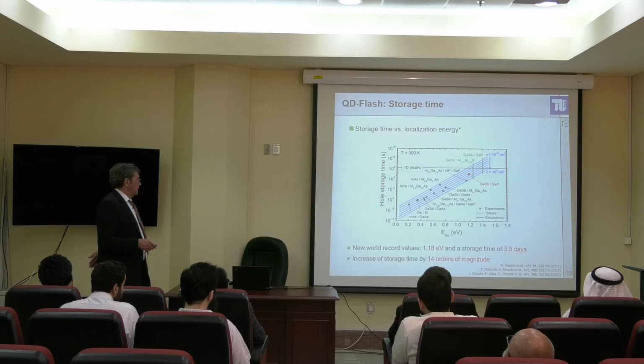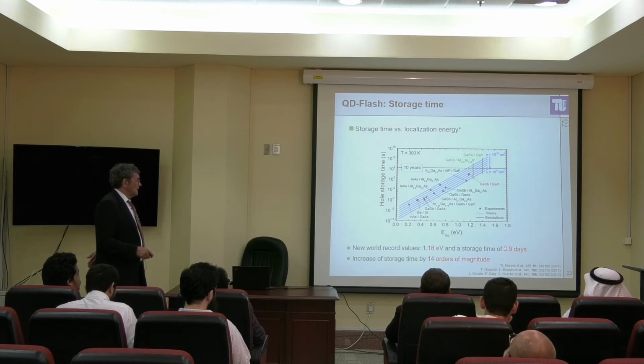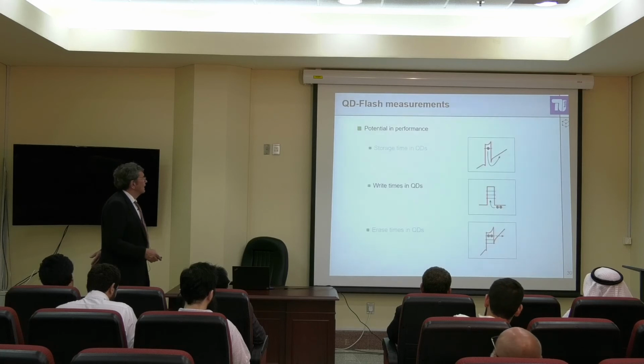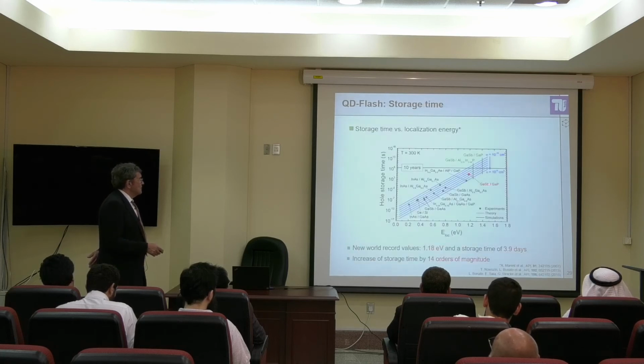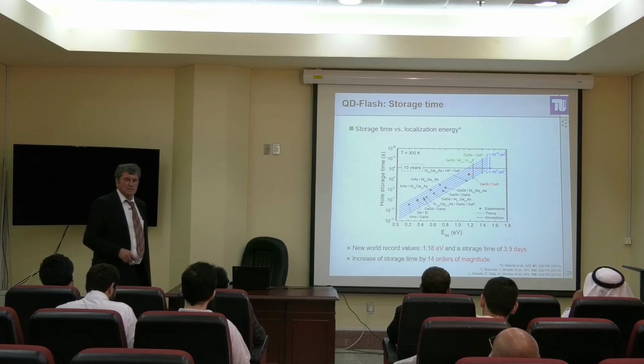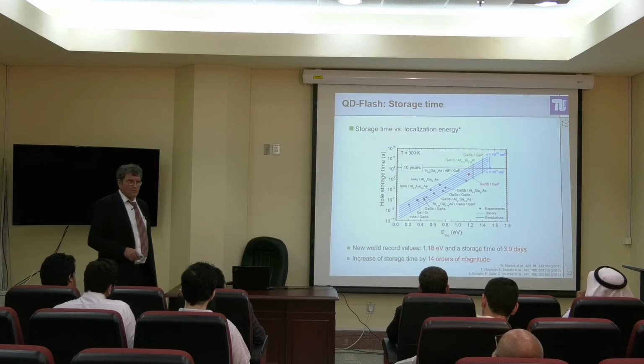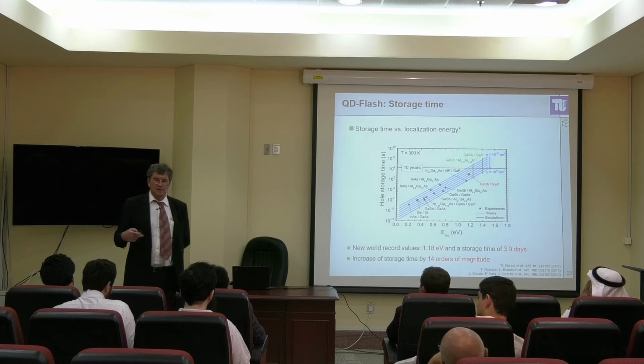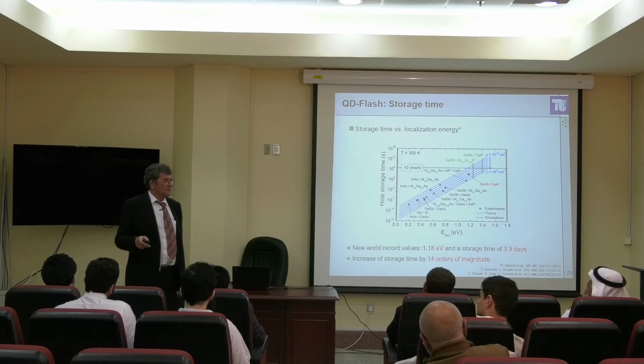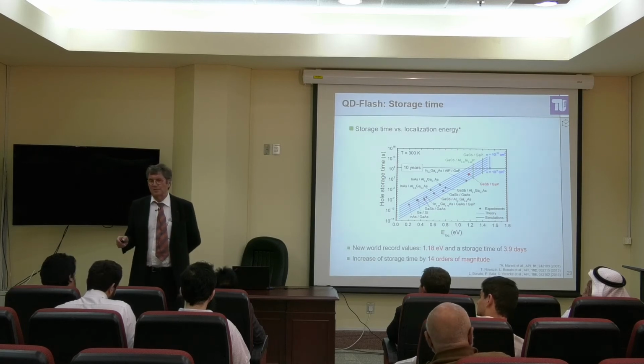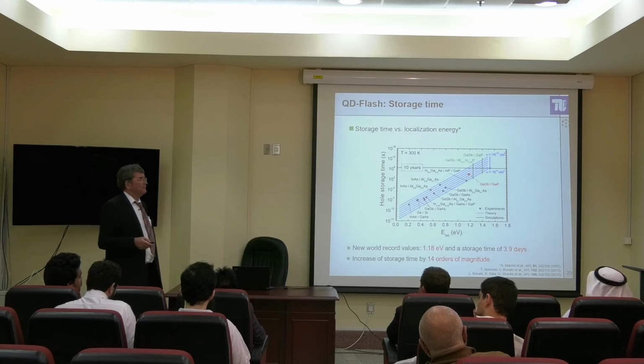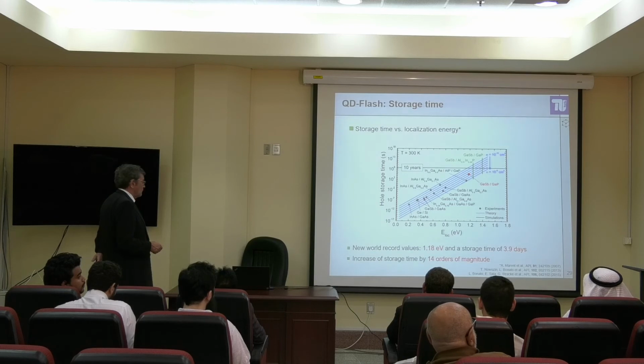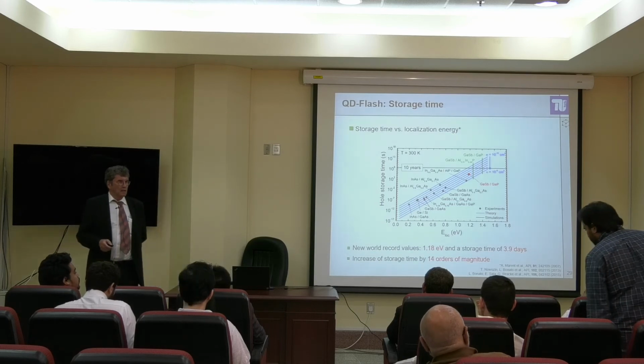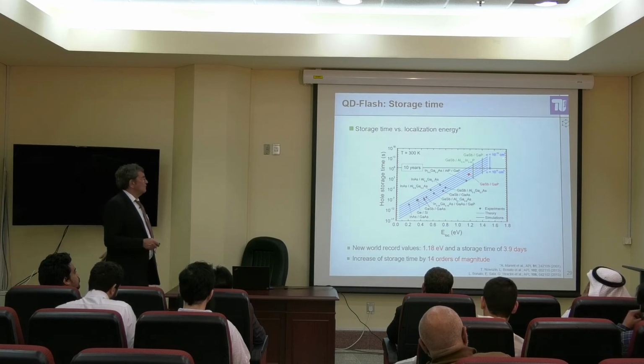We have increased by now. We are here at 4 days. This is the very last achievement. We have increased the storage time by not 10 but 14 orders of magnitude. And the next step is replacing the gallium in the gallium phosphide by aluminum, using aluminum phosphide. Now, for somebody who is familiar with semiconductor technology, fortunately nobody is here, because he would immediately yell and say it's impossible. It is possible. Everything is possible. You just have to work on it for some time. And with aluminum phosphide, and here we're working with a group in France, we will manage to go up here.